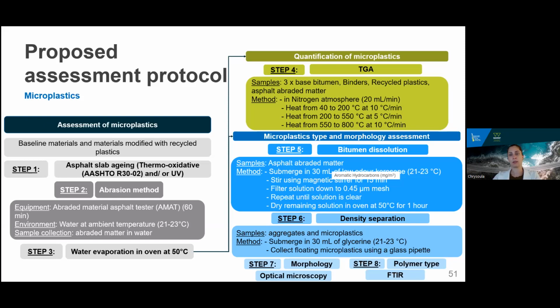For the quantification of microplastics, thermogravimetric analysis was found appropriate. Due to the small amount of material analyzed per specimen by this method, a minimum of 3 specimens should be considered per sample group, and their average should be reported. Bitumen dissolution and density separation can then be used on the remaining abraded matter in order to assess the morphology of the released microplastics and find the type of plastics present.